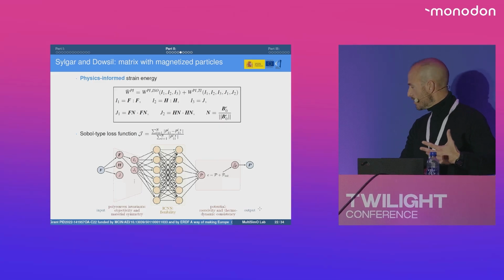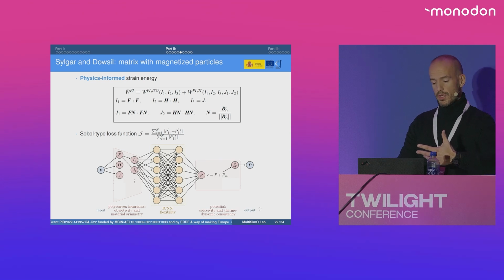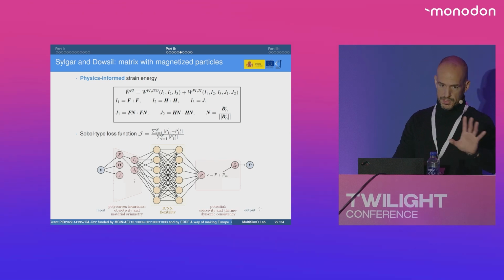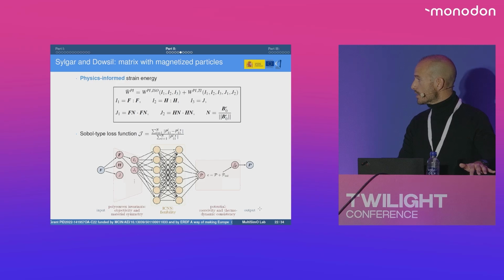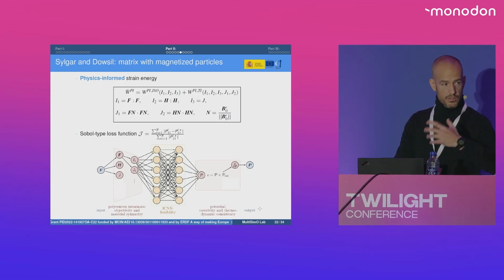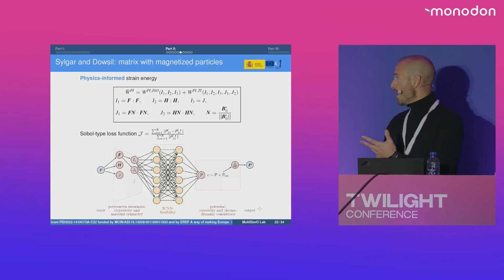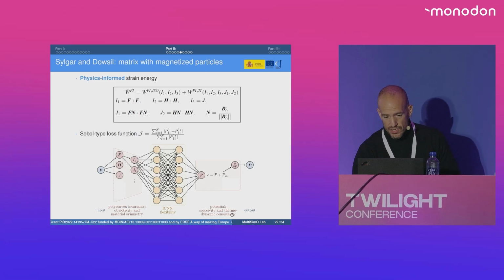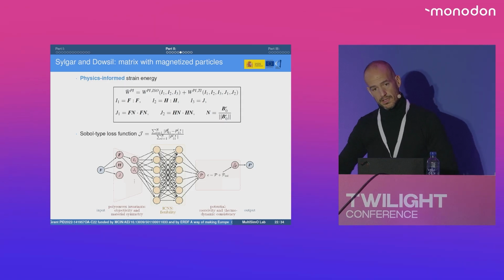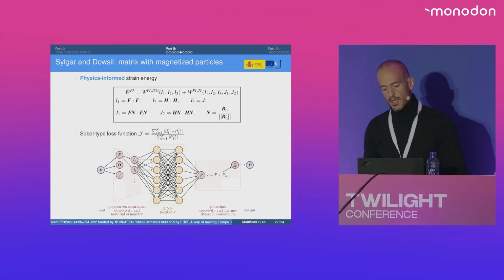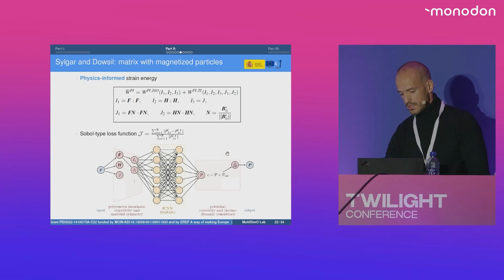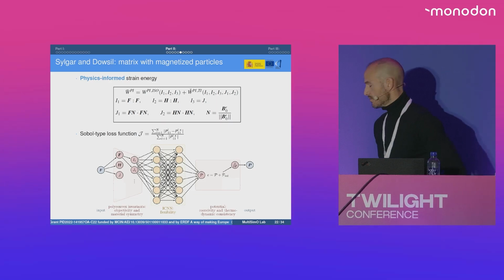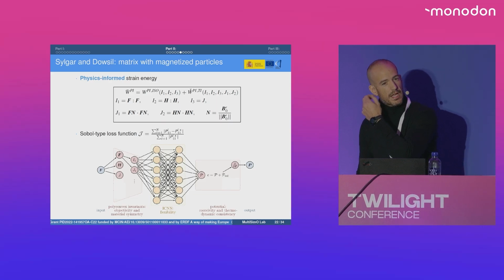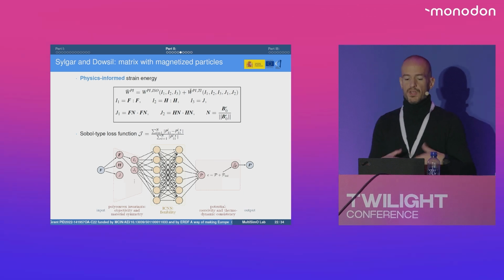Okay? The way I created my strain energy density was through machine learning using neural networks. Okay? So I created a neural network whose inputs were invariants of the deformation, and in order to obtain the biases, weights, and so on of this neural network, of my strain energy density, I minimized, essentially, you can see it here, the difference between the stress data provided by our colleagues in the lab and the stress data derived from this strain energy density. So essentially, it's a Sobol type neural network. Okay? So now we can do simulations.